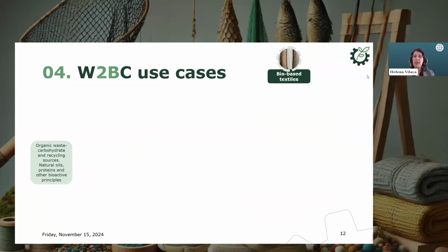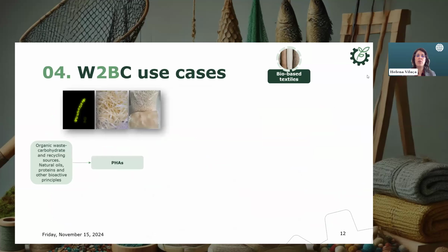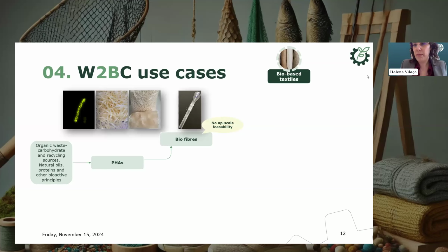Now going to the bio-based textiles, the textile value chain. Again, here we started with the carbohydrate wastes and different bioadditives to produce the PHAs, same as before. And with these PHAs, we have developed some bio-based fibers using wet spinning. As an alternative process to the melt spinning, we tried to obtain fibers through a different process to check their properties. However, in this case, we always needed to use organic solvents for this process, so it's not feasible to upscale this one, so we abandoned this alternative.